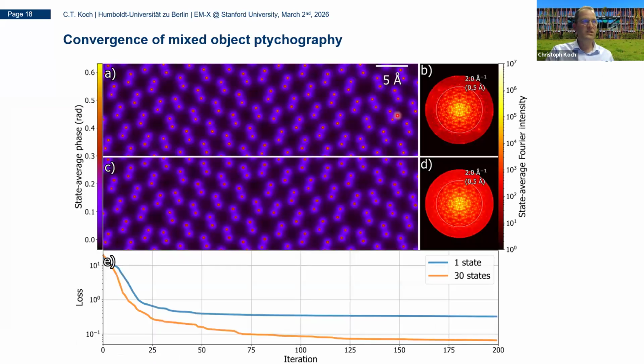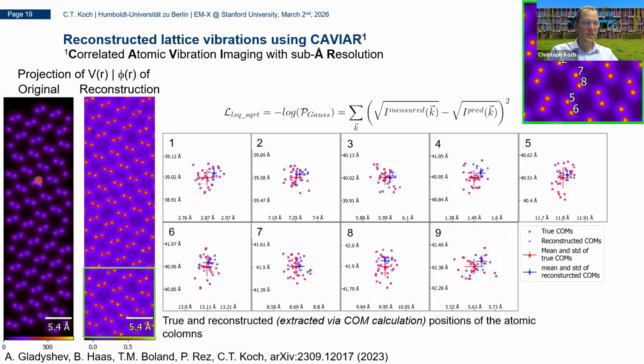And what comes out is that this would be a single object reconstruction, where you have a diffraction pattern that includes thermal diffuse scattering, where you can see there is this high frequency noise in here. But when you then have multiple objects and you average over them, you can see that you have also information out to higher angles, and also this noise at the high angles is reduced. So this is the average reconstruction. But we can also, of course, keep the individual objects and look at what they look like.